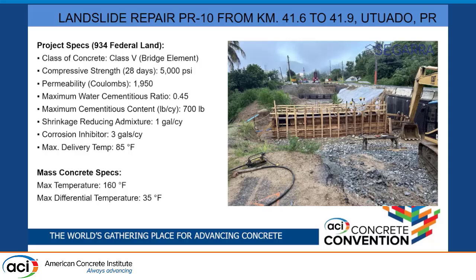We used a class 5 bridge element concrete class, compressive strength of 5,000 PSI, permeability per ASTM C1202 of 1950 coulombs, a maximum water cementitious ratio of 0.45, maximum cementitious content of 700 pounds, shrinkage reducing admixture 1 gallon per cubic yard, corrosion inhibitor 3 gallons per cubic yard, and the maximum delivery temperature was 85, maximum temperature on the concrete 160, and the maximum differential 35.